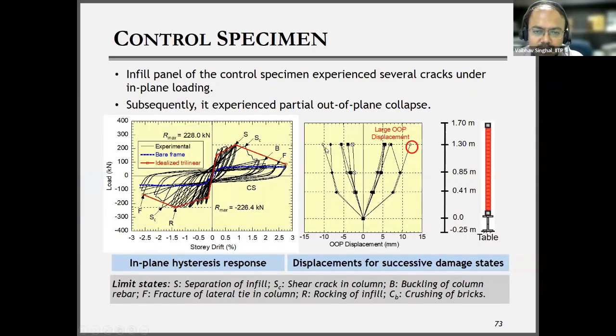In the control specimen, the first curve shows you the in-plane response, and the second curve shows you the out-of-plane displacement response. We have seen a large amount of out-of-plane displacement with the in-plane damage. You can see that the displacement was going more than 10 mm. Even for a higher cycle, which I have not plotted here, the displacement was quite high. It was even more than 30-40 mm.